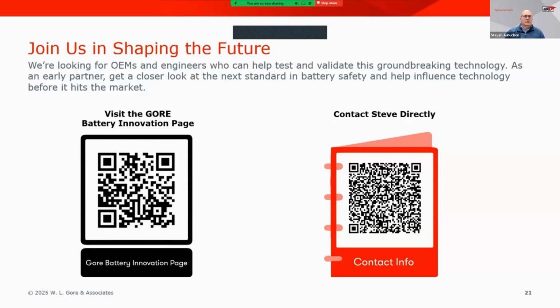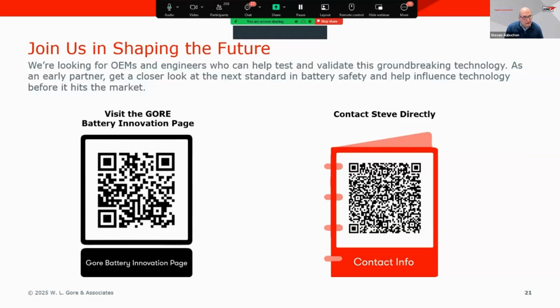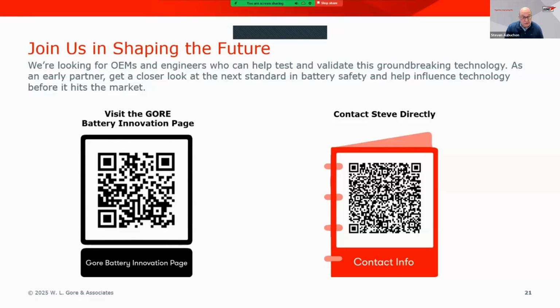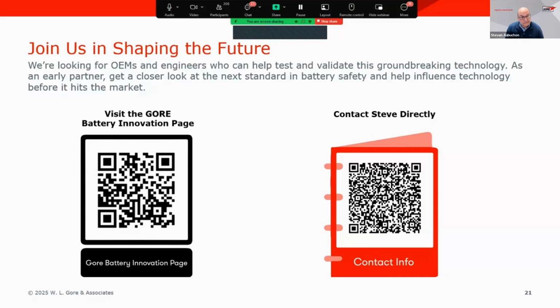And in terms of thicknesses, we intend to produce this nominally at 1 millimeter thickness. We find that that is a pretty good starting point for most applications. If thickness greater than that is required, you can layer various materials together. We also have the ability to produce at slightly lower thicknesses, down to about 500 microns, but ideally we would offer this material at 1 millimeter thicknesses initially. That's our nominal thickness, but we're happy to have discussions with interested customers if variable thicknesses are interesting.